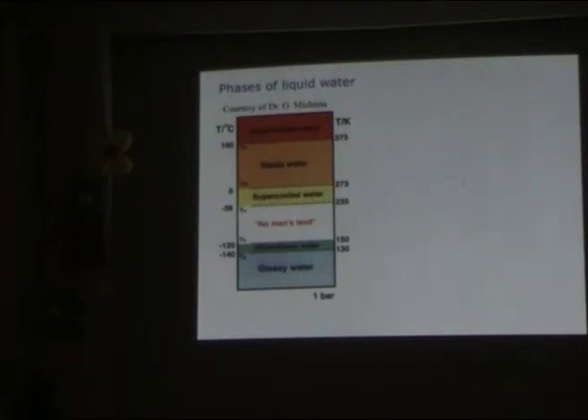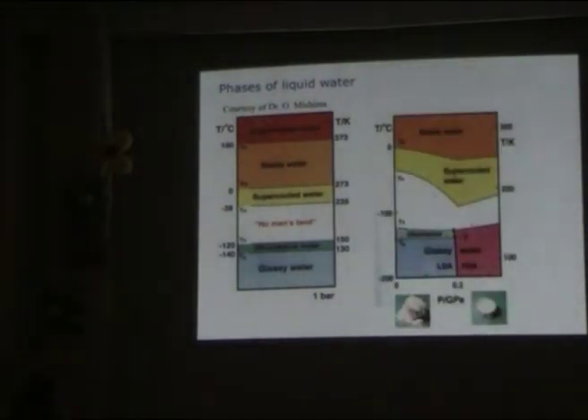And then you can see that if you pressurize this ice water down to really high pressure, from 1 bar to 0.5 gigapascal, for instance, you can see that this amorphous water goes through a first order phase transition. You can see that when you compress it, there is a really sharp transition in terms of volume. This is just an illustration for the low density amorphous, where the local structure looks like ice. And there's another one, called high density amorphous. The structure is not similar to a tetrahedral structure.